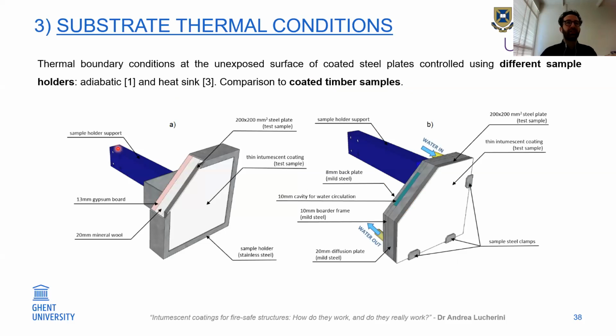In order to replicate the different thermal boundary conditions at the back of the plate, I used different sample holders. The first one is to reproduce a sort of adiabatic or insulated condition. You can see here my steel plate and the sample holder. At the back, I have 20 millimeters of mineral wool and then gypsum plasterboard. And this reproduces my insulated conditions.